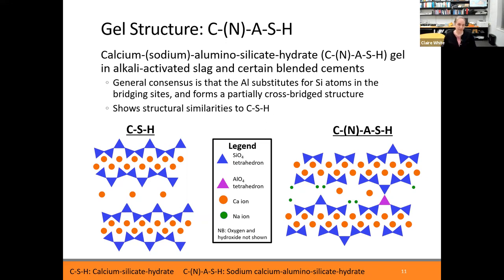Okay, so on the left on this slide is a representation of the calcium-silicate-hydrate gel without showing oxygen atoms, without showing hydrogen atoms, but just showing the calcium ions and these silicate chains. What's known is it has this layered structure at the nanoscale. These chains are of finite length that can be quantified using nuclear magnetic resonance. And then there's these calcium oxide layers, and these calciums are interlayer calciums, and they're solvated by water molecules. So this is C-S-H, and the structure of C-S-H is quite well known. If we add sodium and aluminium into these systems, we know some things.